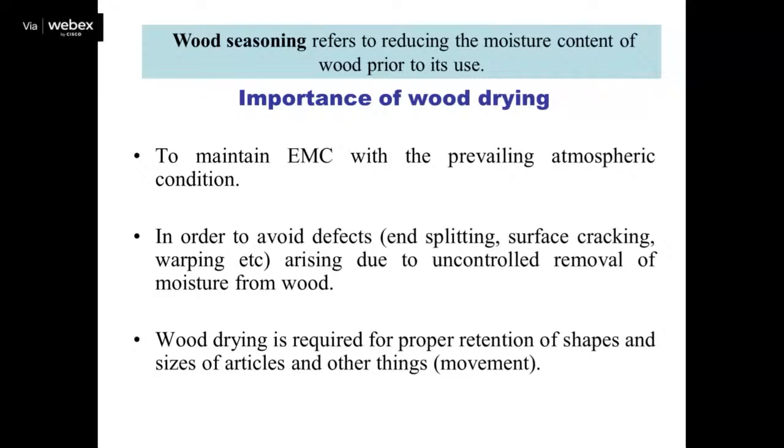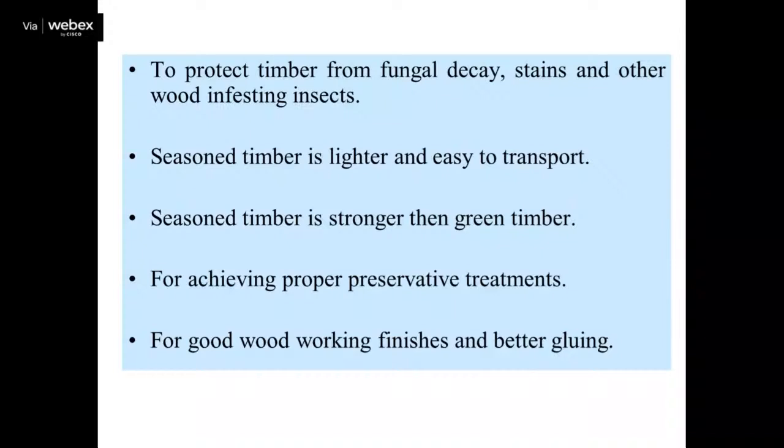And what is the importance of drying? The first and most important factor is that it maintains the equilibrium moisture content with the prevailing atmospheric condition. It is very important that the wood should be dried and retained at the equilibrium moisture content where it is going to be used. Also there are different defects if the wood is not dried properly and we are manufacturing the product out of it. There are chances that different defects may arise, and therefore in order to control those defects, it is important to dry the wood. It is also required for retention of shape and size in the articles, and minimizing the movement in the products. It also protects the timber from fungal decay, stains, and other wood-infesting insects.